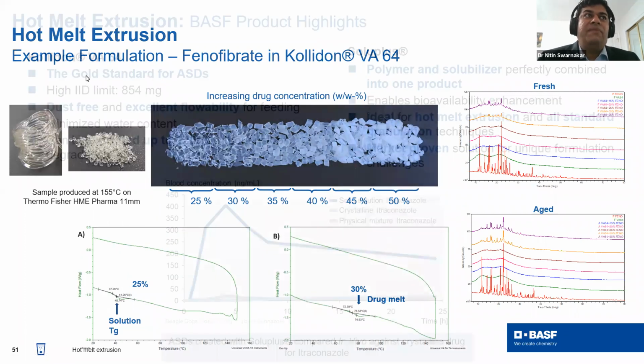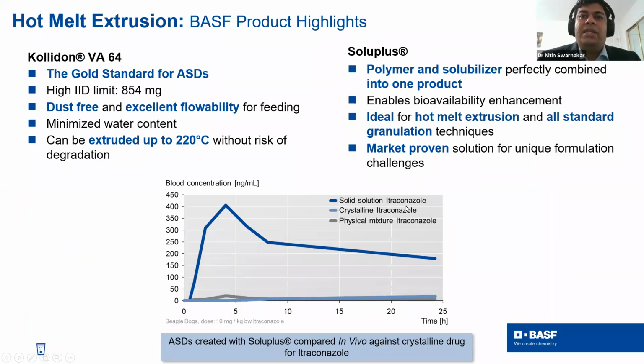And what we want to convey here is that we have done a study using itraconazole, and we have solubilized the drug. You can see here the crystalline drug is not getting absorbed, the physical mixture is not getting absorbed, but HME is getting much higher bioavailability compared to the free drug and physical mixture. So this is a great in vivo example, from a study which we have done. So we can use two polymers. We have VA64, which is the gold standard. This is very important because we need more polymer to dissolve the drug. And you can see the IID limit is 854 mg per day approved.